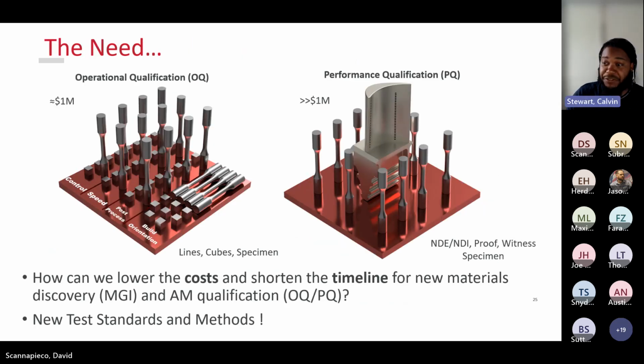Now, in the AM official NASA, ASTM, SAE qualification standards, there are 3 steps. There's installation qualification, where you install your machine, you calibrate it, and say okay, it's qualified in place. Then there's operational qualification, where you load your powder and you print probably 6 build plates of lines, cubes, and specimen to verify that you can get consistent properties with that powder on that specific machine. And then you go to performance qualification, where you start to print parts, you do NDE, and you print witness samples.